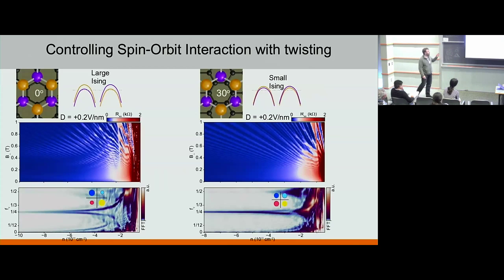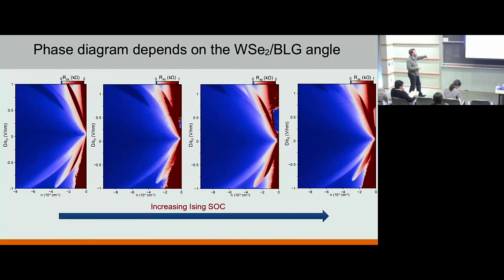There's an alternative way to do this, by crossing of the Landau levels in fields, and we did all the cross-checks that we could, and they produce consistent results. So we can confirm this picture that roughly at 0 degrees the spin-orbit coupling is the largest, and here it is the smallest. Now, if you take all these devices and map out the phase diagram, what you get is that with higher Ising spin-orbit coupling, your superconducting pocket actually moves to higher and higher displacement fields.